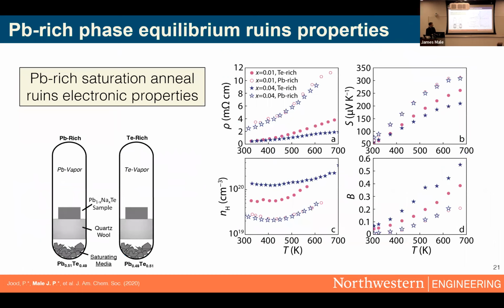I also performed the same sort of phase equilibrium studies in these samples, where I did saturation annealing to make them lead or tellurium rich. What we find is the ideal phase equilibrium is kind of opposite the N-type samples. So now tellurium rich saturation annealing gives you better doping and better performance, whereas lead rich saturation annealing kind of ruins your properties a bit.